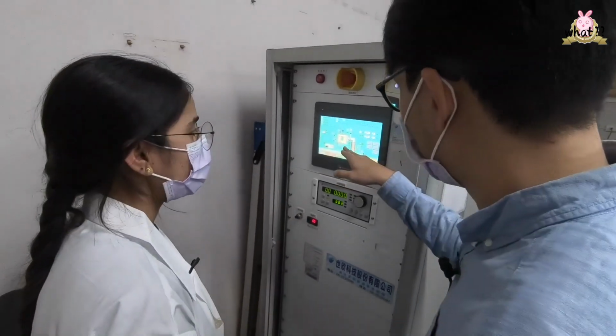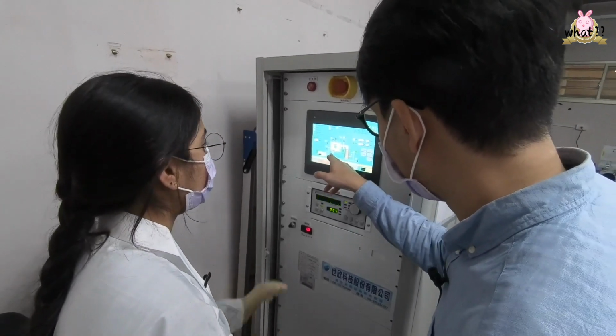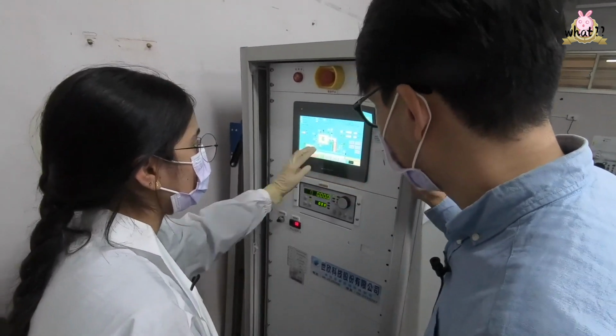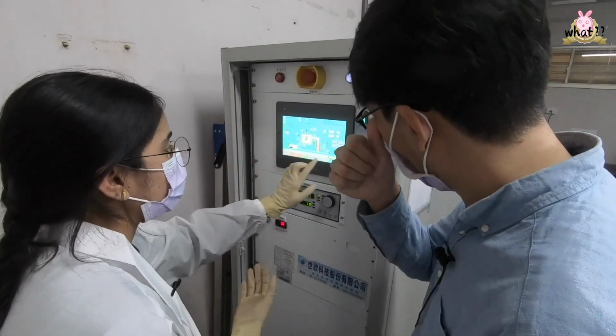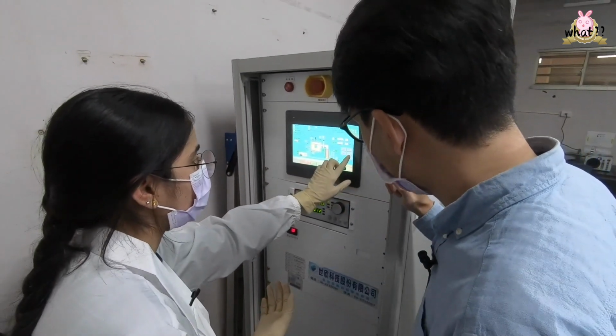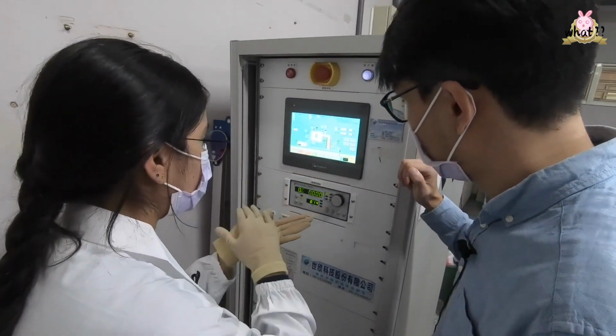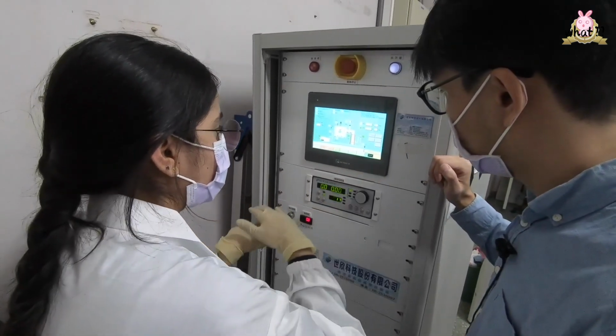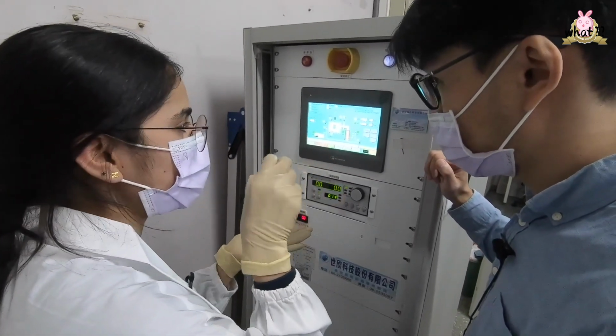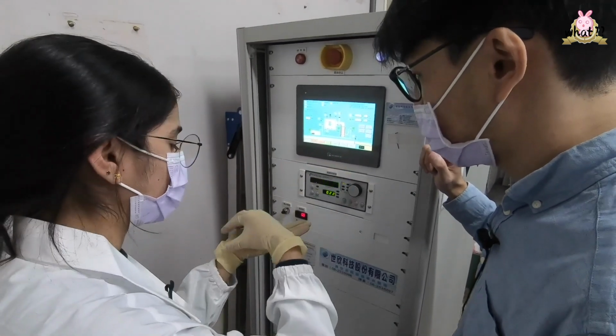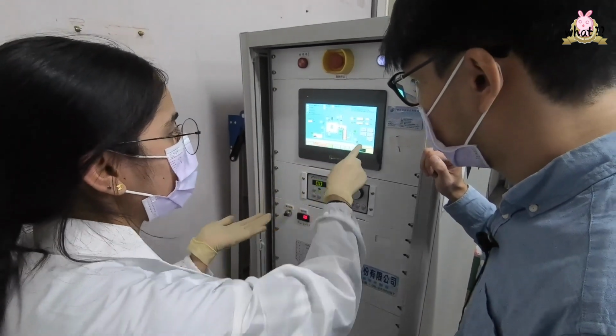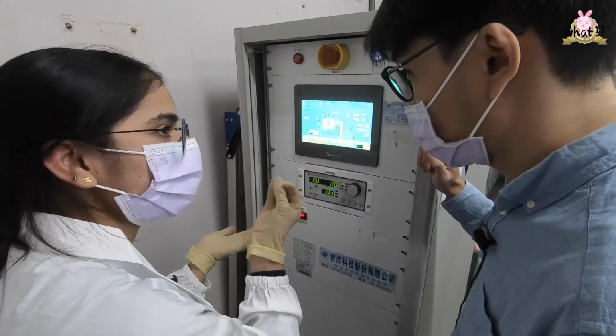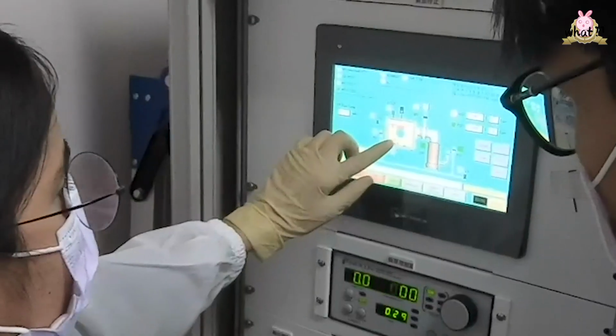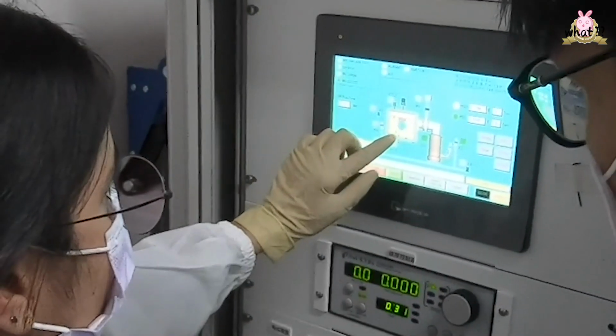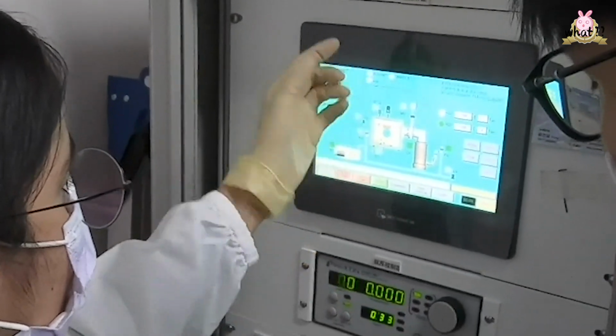So after the chamber is ready, we will open this one, the shutter for the silver thin film, and then we can open this ETH2. Here we will give power, and we already put our silver beads on the tungsten plate. So the silver will start melting and evaporating. Our sample is here. Yes. And silver is here. Yes. So it will evaporate to here.